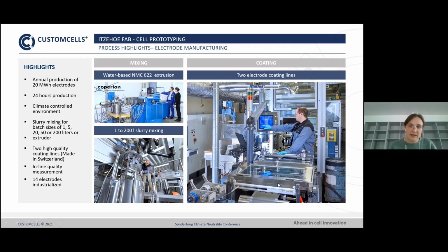And the application on the electrode foil, you can see that's here on the lower half of the picture. There is the bare foil, and here behind my colleague there is the application of the red slurry on the foil. On the anode side, we can do that with water. On the cathode side, we usually do that with organic solvent, which needs to be dried afterwards.